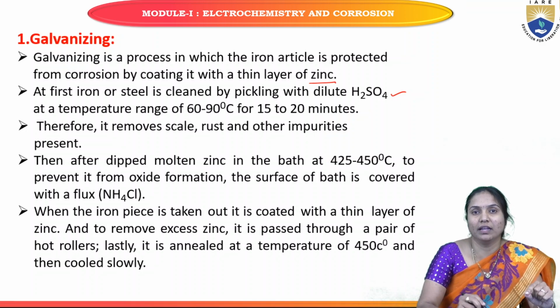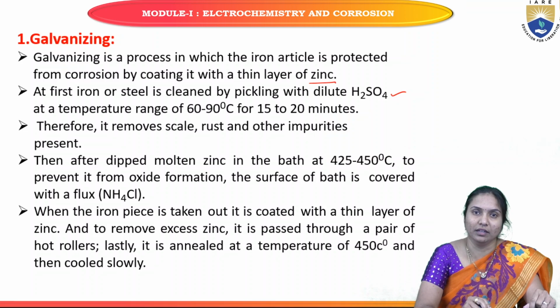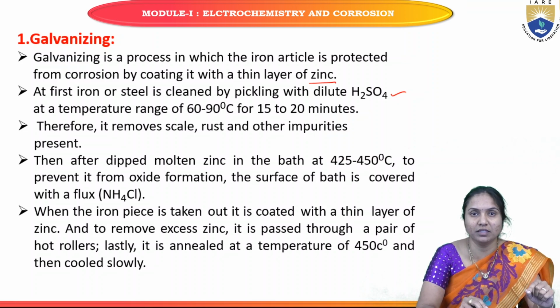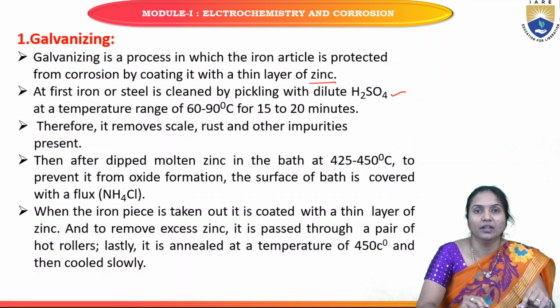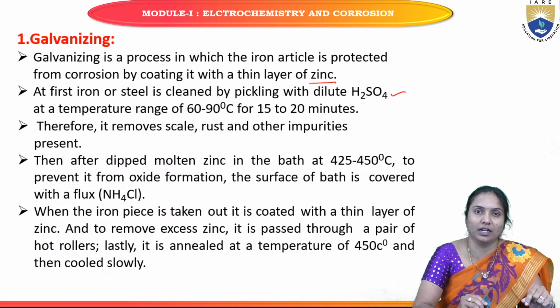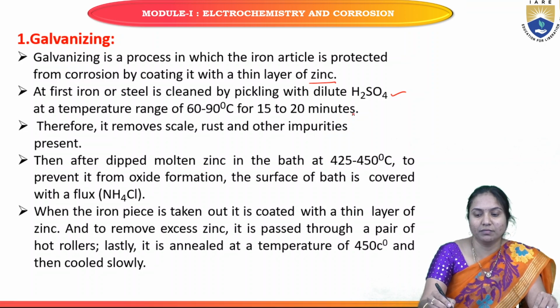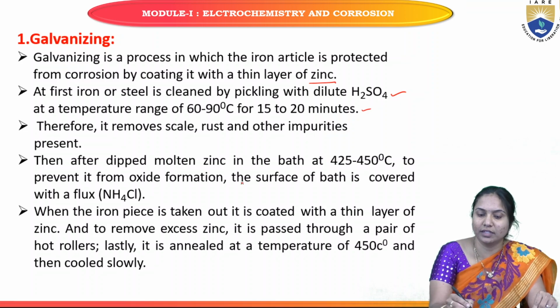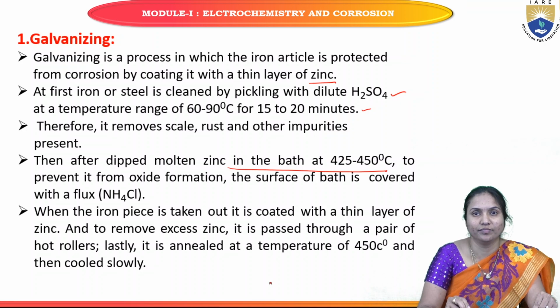So first of all, what is the meaning of galvanizing? Zinc coating on base metal is called galvanizing. Here the base metal is the one we want to protect from corrosion. Generally this type of coating is applied on iron or steel material. The iron or steel article is first cleaned with dilute H2SO4 to remove any impurities present on the base metal surface. Next, after removing the impurities, the iron metal is dipped in a molten zinc bath, maintained at a temperature range of 425 to 450 degrees centigrade.